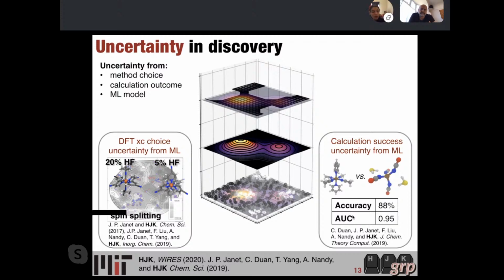And so what we found was that both the more transferable model and the model that could achieve better accuracy was one in which we fed in properties of electronic descriptors, things like the metal organic bond order, as well as the metal charge. We actually used just properties coming from the wave function and the geometry, the gradient, and that could achieve 99% accuracy. And models got more accurate the more time steps from the optimization you fed it.